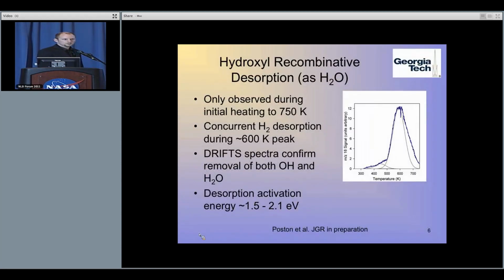So now to our actual results. The first thing we did was to heat the sample to remove any water that was native to the sample already. We did this as a temperature program desorption experiment so we could monitor what came off. And we saw this peak that you see where, again, I've plotted the desorption rate of the water signal from the quadrupole versus temperature. And we have this peak centered at about 600 Kelvin.